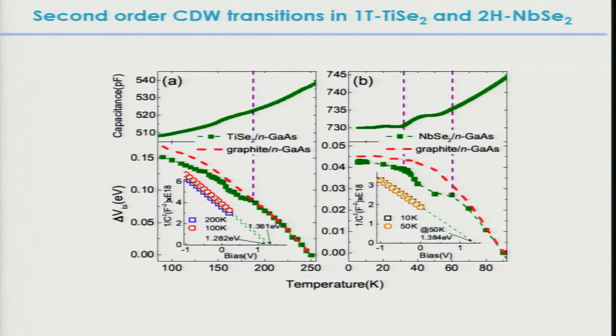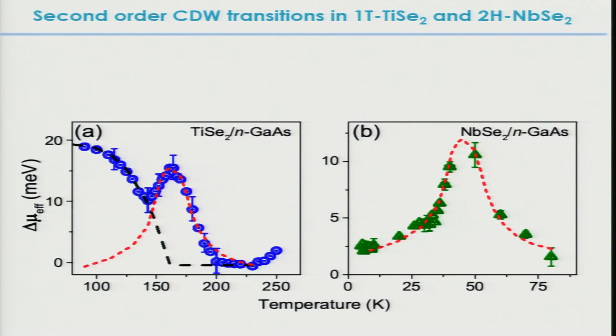We do the capacitance measurements, and again, we do a comparison to a normal graphite counterelectrode, so that we can normalize these bumps. And when we normalize them, I'm going a little bit speedy here, but I just want to show you the final result. When we normalize these bumps, we see that titanium diselenide has a high, this is where the CDW starts. It's a semi-metal here. There's no CDW in this region.